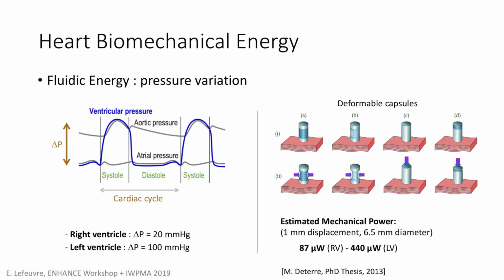We can harvest it using deformable capsules. It looks like the most convenient way to get displacement and force, so energy. The deformable part is the blue one. The most convenient for us looks to be having the extremity here that can be compressed. If we look at 1 millimeter displacement of the mobile part of the capsule with respect to the rest of the capsule, and 6.5 millimeters in diameter, we can harvest up to 87 microwatts in the right ventricle, which is quite a lot compared to what we need.